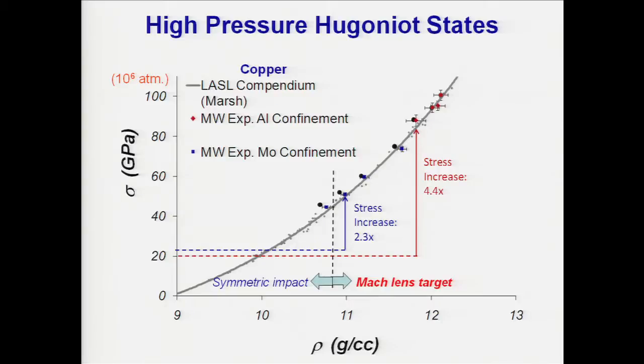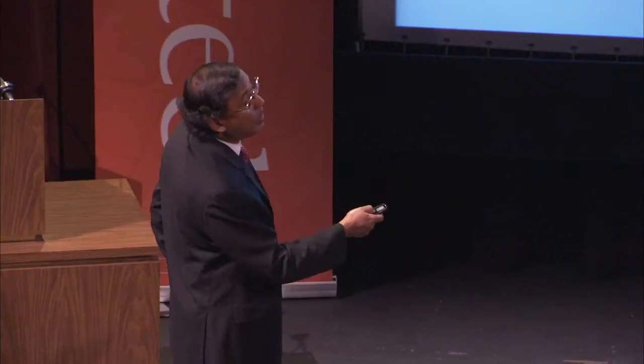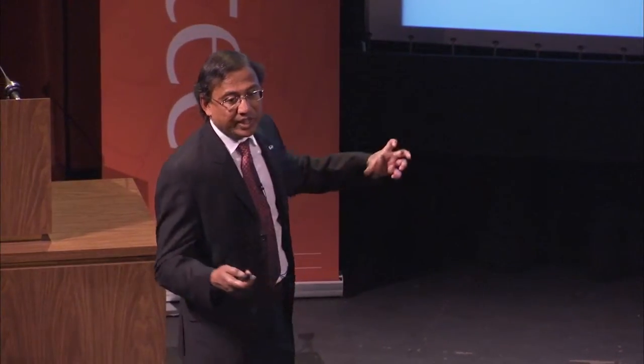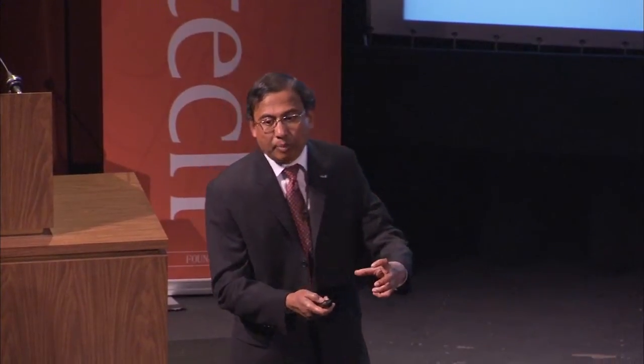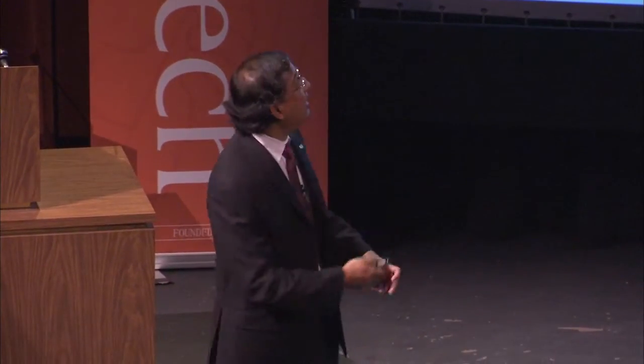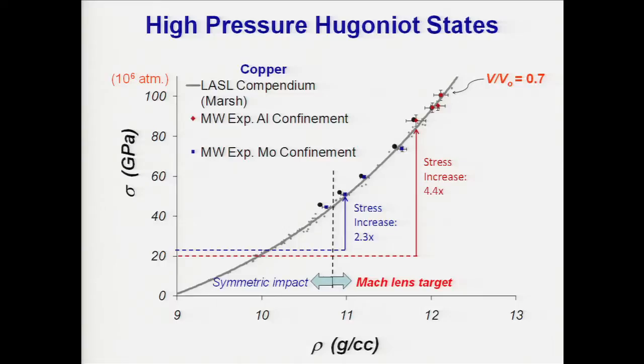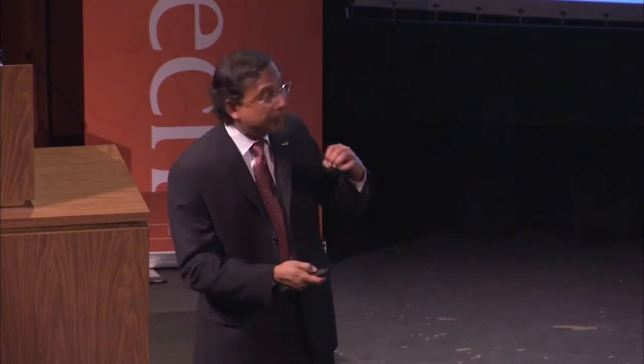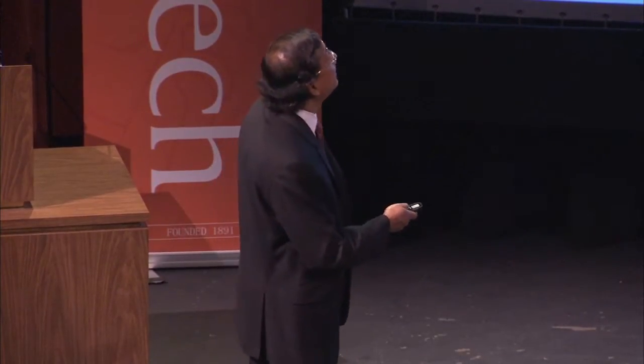But now, because of this Mach lens target, I can increase the stress significantly, and we can achieve, with this kind of simple idea, a volume compression of about 30%. So we can change the volume of a piece of copper by 30%, and it needs about 1 million atmospheres. But we do this only for 1/1,000,000 of a second. So it is a very, very short amount of time we are probing the material response.